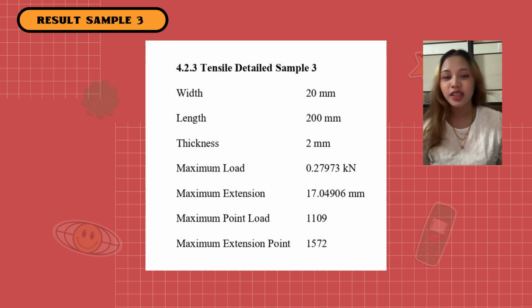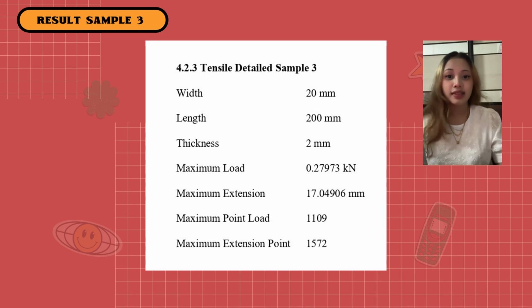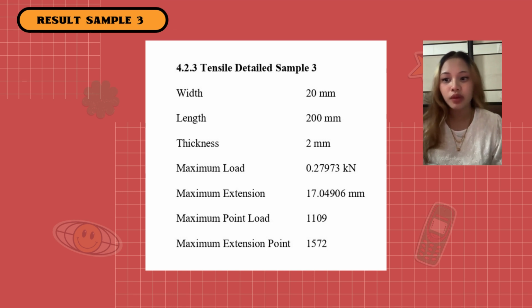And this is the last sample, which is sample 3, and this is the tensile detail. Width, length and thickness same as sample number 1 and sample number 2, which is width 20 millimeter, length 200 millimeter, and thickness 2 millimeter. For maximum load 0.27973 kilonewton, and then maximum extension 17.04906 millimeter. Maximum point load 1109. Maximum extension point 1572.